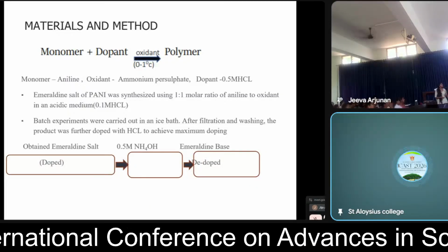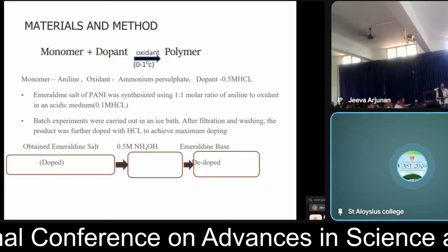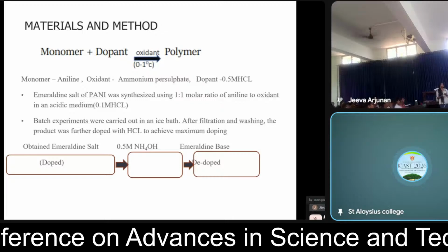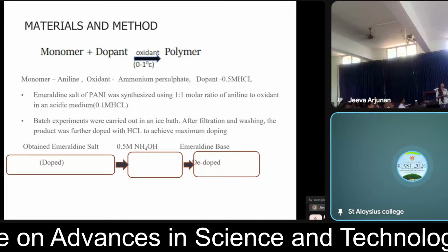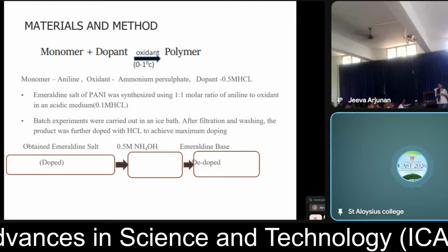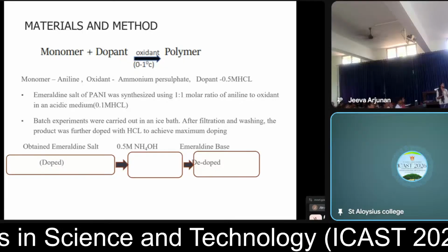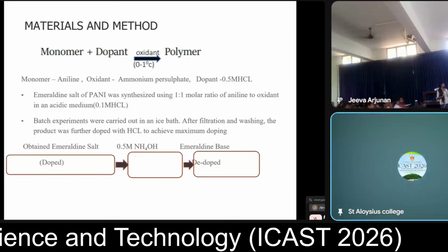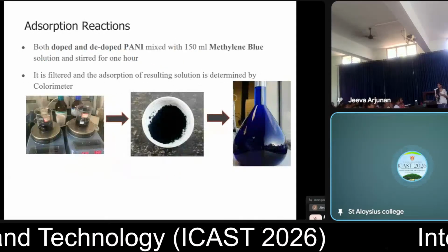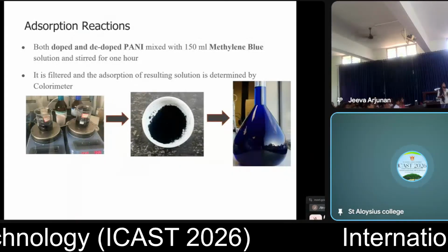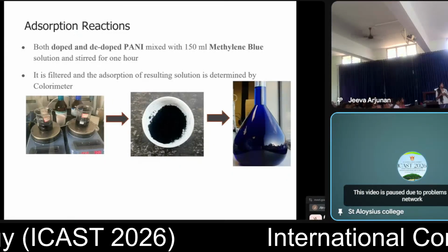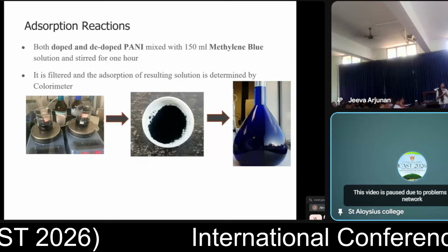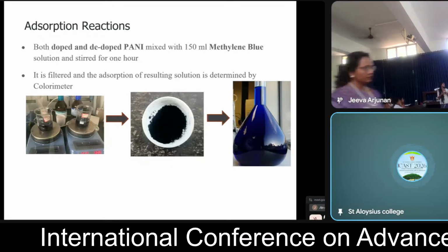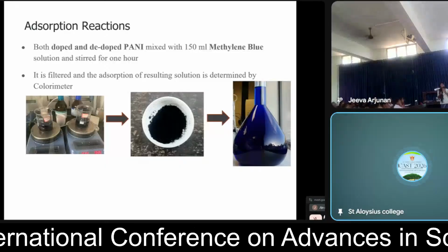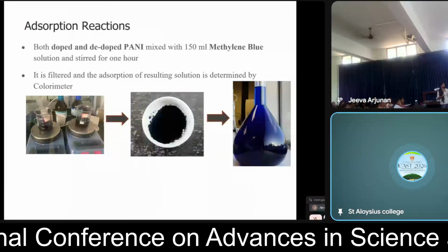So for the method, we take aniline as the monomer and ammonium persulfate as the oxidant, and here we use HCl as the dopant. The emeraldine salt was first synthesized using HCl, and we dedoped it using NH4OH. And we get both doped and dedoped forms of polyaniline. These doped and dedoped polyaniline were mixed with the methylene blue solution and stirred for 1 hour. After the filtration, we determine the adsorption of the resulting solution using colorimetry.